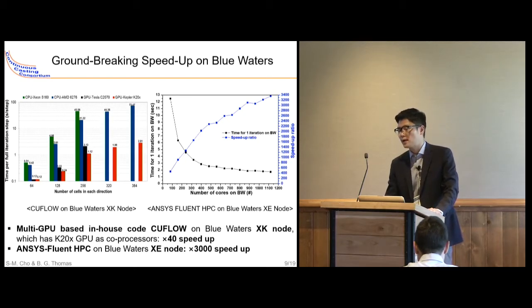And we also tested ANSYS Fluent on Blue Waters XE nodes. We tested LES coupled with the VOF model, and that model showed over 3,000 times faster performance compared to the workstation simulations. This speed breakthrough enabled us to consider a much finer domain and a smaller time scale. And we can also calculate many cases at the same time. This is very important for the parametric study to figure out practical strategies to improve this process and to find solutions to reduce the defects.